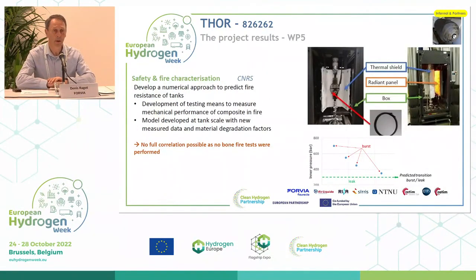Regarding the material behavior in fire, the CNRS P prime has made a characterization of the degradation of thermoplastic resin in fire, and developed a model to be able to make a leak before burst design. But as I said, we have not been able to make bonfire tests with hydrogen, so the model is not correlated right now.